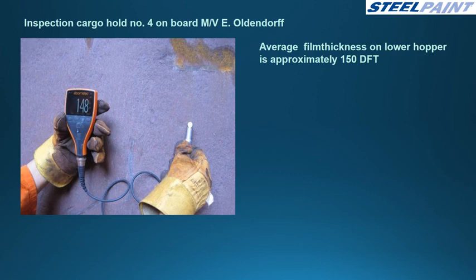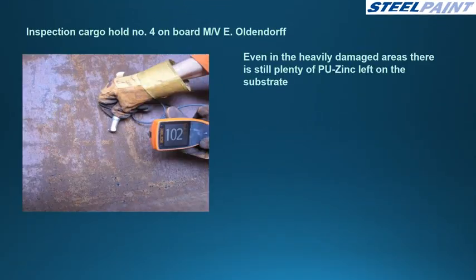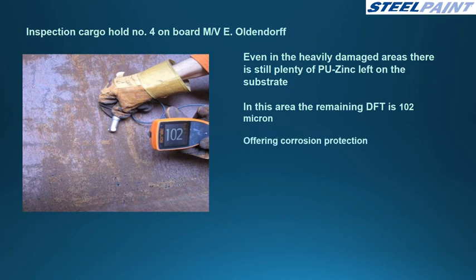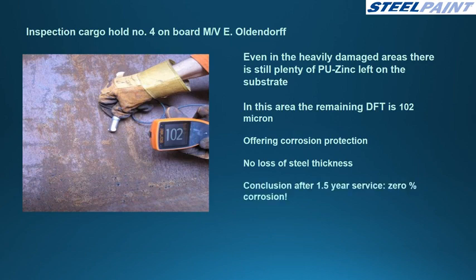The average film thickness on the lower hopper is approximately 150 microns. Even in the heavily damaged areas, there is still plenty of PU Zinc left on the substrate. In this area, the remaining dry film thickness is 102 microns, offering corrosion protection. No loss of steel thickness. The conclusion is that after 1.5 years service, there is 0% corrosion.